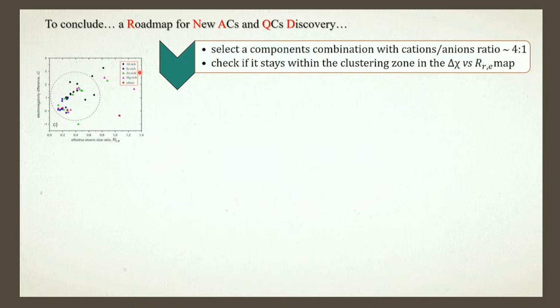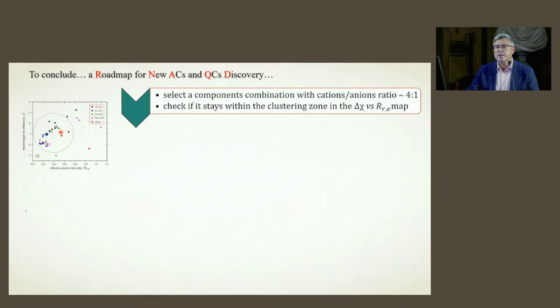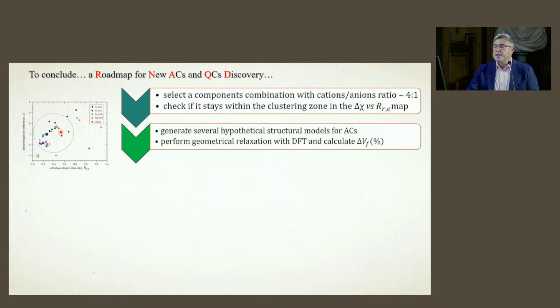If they fit to this region, probably it's a good idea to go further and generate some theoretical approximants with wanted composition and structure, and relax it with DFT to get the effective volume parameters.